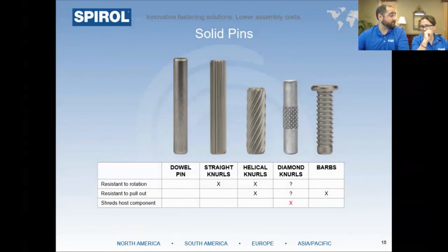And one thing I do want to mention is that if you're using solid pins, it's really important that the solid pin is harder than the hole it goes into. True. So the solid pins are typically used in press fit applications, and there's two different ways to do that. The first is with the use of a dowel pin, where the pin has a larger diameter than the hole that it's going into, and it's displacing the material. Another way to use a press fit is to have a retention feature like a knurl or a barb, as you can see in these images.